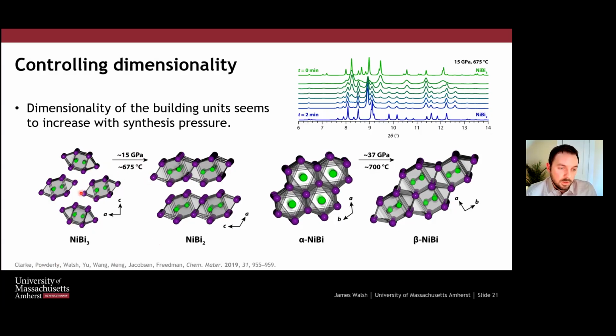What's interesting is that if you compare the original nickel bismuth, you see these one-dimensional, pseudo one-dimensional building units. You see the 2 nickel surrounded by these 6 bismuth, which extends into the screen. It's not quite that simple, but you can see this moiety. What we find is that when we apply pressure, the higher pressure we go to, we actually increase the dimensionality, so we could say that we're controlling the dimensionality with pressure. These are pseudo one-dimensional. The moieties appear in this higher pressure system as 2-dimensional sheets. And then the same moieties appear in the beta nickel bismuth that I showed in the previous slide as these 3-dimensional connected frameworks, basically. That's an interesting observation that, again, Sam published on.